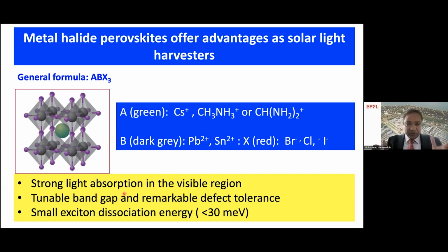So it absorbs all the visible light. In the next slide, you will see what the absorption spectra look like for these materials, and the tunable band gap of these materials. So how do we tune the band gap? Depending on the materials which we select, cesium or formamidinium, lead or tin, bromide, chloride, and halide, we have beautiful possibilities to tune the spectral response onset from say 1.2 eV to almost 2.25 eV. So you can say these materials are highly tunable.